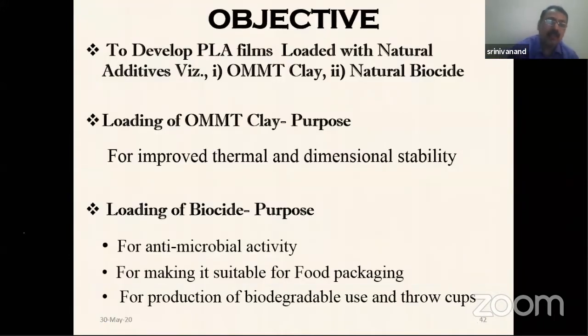Another thing is, as I told you, we were able to develop some biocide loaded films. And this biocide is very interesting. It's a very proprietary item, so I don't want to name the biocide. The biocide has got some acid, which has a lot of properties like antibacterial, antiviral, anti-HIV, and all these properties are exhibited by this particular acid, which is present in the biocide. We have incorporated that biocide and we have made a film. Similarly, we have also incorporated organically modified montmorillonite clay.